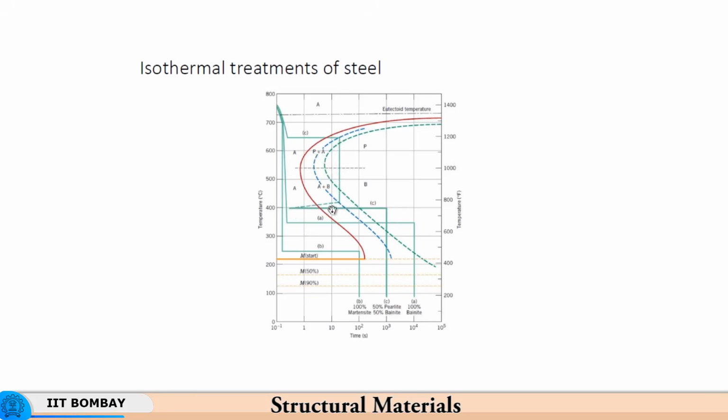then you will have austenite plus pearlite here, and then this effectively will go back to this type of situation, because now you have quenched it. There is no change in the phases, because these phases form purely because of diffusion, and by cooling it very rapidly, almost vertically, almost instantaneously, you have not allowed any diffusion to take place. So, the result is that the austenite plus pearlite, whatever was available here, is available in the same percentage over here as well. And then you are taking this to the completion of transformation over here.